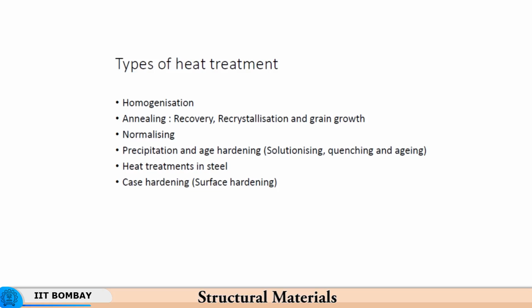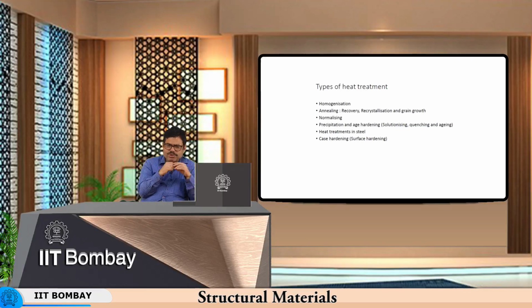So, when I had solutionized the material, everything was in solution, the same set of alloying elements uniformly distributed in a solution, but now when I got them to precipitate as intermetallic compounds, then I got a higher hardness, because these intermetallic compounds are harder than the matrix, and they are the ones which impart hardness or resistance to plastic deformation through the process of aging. So, there are plenty of heat treatments in steel which we will see soon.